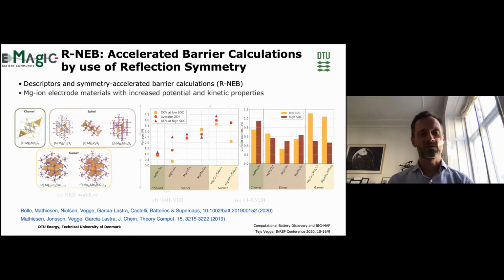So out of this study for potential candidates to compete with the Chevrel phase, what Felix discovered was a couple of spinel structures that had higher OCVs at both high and low state of charge, and a couple of garnet structures that are potentially interesting. And from this kinetic analysis, we saw that of the spinel structures, 2 particular candidates had a combination of both higher OCVs and faster transport kinetics.